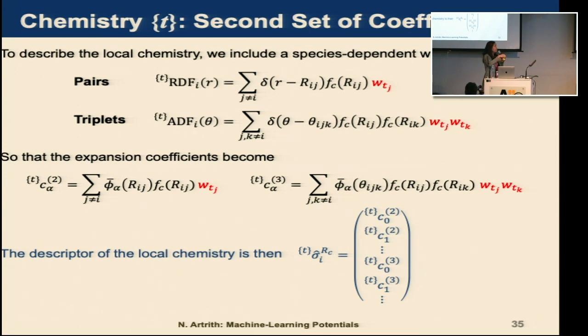we use just the number 0 to multiply with the function that you have at the beginning. And if you have two chemical species, we use -1 and 1. And if you have three chemical species, we have -1, 0, and 1, and so on. That way you can get the information that you have different types of chemical species. Even if you have one chemical species, you get the number 0 in your second set, which shows that there is only one chemical species in your structure.